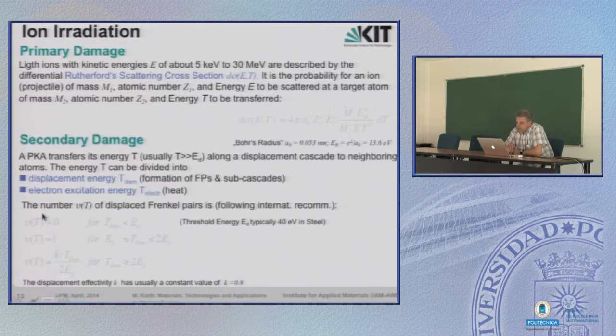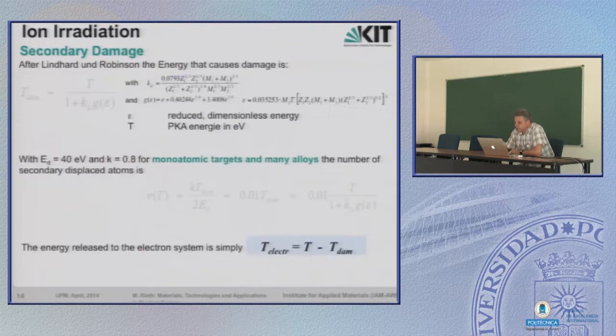Now, it is quite easy to introduce a number, nu, which gives the number of produced Frenkel pairs, because this is the most important damage which starts. So, nu, depending on the energy of a knock-on atom, is increased depending, of course, on the energy. If the energy of the knock-on atom is below the threshold, which is required to produce another damage, then, of course, the number of Frenkel pairs is zero. If it's between the damage threshold and twice as high an energy level, then nu is accounted for one Frenkel pair. And for larger energies, it's a simple linear extrapolation. That is, the higher the energy, the more Frenkel pairs are generated.